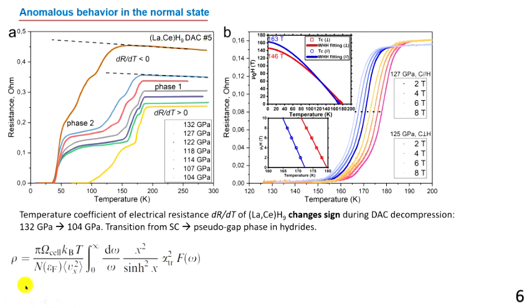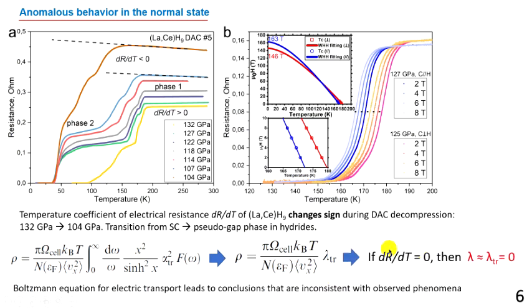If we apply to this situation the Boltzmann transport equation, at relatively high temperatures, we can find this linear dependence as usual, and the temperature coefficient of resistance will be proportional to electron phonon coupling coefficient. And at one certain point of pressure we expect to see a zero temperature coefficient, which means absence of electron phonon interaction and the zero electron phonon interaction strength. So the main conclusion from such situation is that superconductivity in hydride and the Fermi-liquid behavior in normal states are in principle incompatible. They are incompatible because superconductivity requires non-zero electron phonon interaction strength, and at the same time we cannot explain the absence of temperature coefficient of resistance if it's only electron phonon scattering. So there should be other mechanism of scattering. So it should be non-Fermi-liquid behavior of hydrides in a normal state.